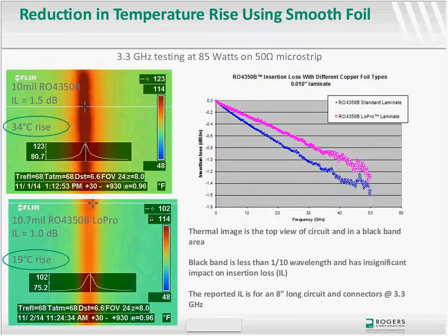In this particular case, we measured a 3.3 gigahertz circuit trace with 85 watts going through the line at 50 ohms. And you can see the difference of temperature rise of that trace relative to the surrounding surface, and how hot it gets with the traditional copper, and then the difference in temperature versus the low pro. So you're looking at almost a doubling in temperature rise difference here. You go from 34 degrees Celsius temperature rise for the regular trace versus 19 degrees Celsius temperature rise in the trace that is using the low pro foil. So besides the losses, you also have the value of temperature.